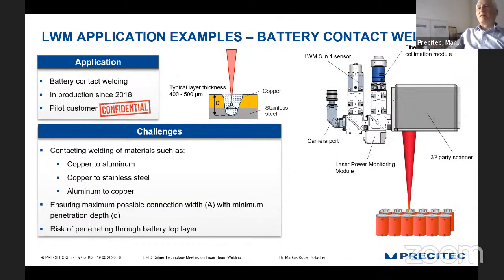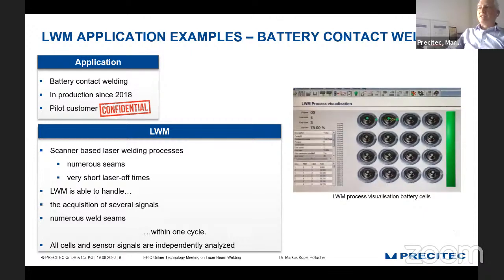As I said, I cannot tell you the customer behind, but what is done here, for those who are familiar with battery contact welding, it's not that surprising that it's copper to aluminum or copper to stainless steel welding or aluminum to copper. You see application here, or the surface of the user interface, where you can see in real time the welding applications and the green or red indication of a good or bad process. So this is what we typically do. We make a picture of the application, a photo of the application, and directly show the customer which part of his process was good or which part was bad.